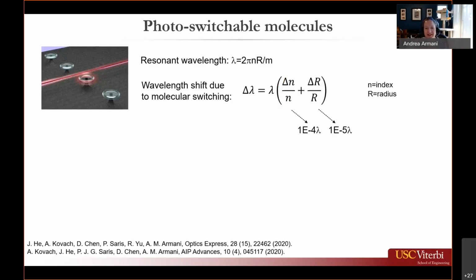Okay, so then the last project is looking at photo-switchable molecules. In a resonant cavity, you can tune the resonant wavelength by tuning either the refractive index or the device radius, because the resonant wavelength is governed by the device radius and the refractive index. So a change in either one will tune your resonant wavelength. We decided to coat the device with a molecule that can change its conformation. Based on some density functional theory calculations, the refractive index change due to molecular reorientation was around 10 to the negative 4 times the specific wavelength we were testing at. The radius change that was induced was around 10 to the negative 5. Therefore, in our system, this resonant wavelength change was really dominated by the refractive index change.